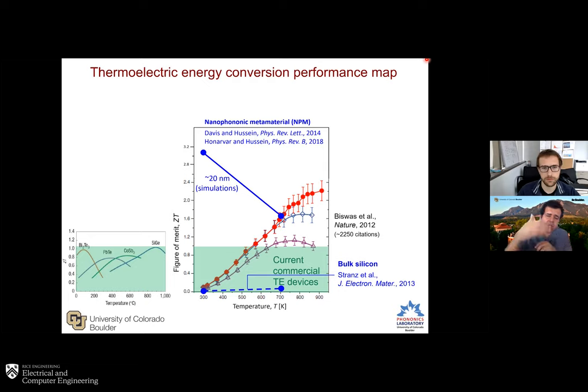So this is, of course, based on simulations. It's not experimentally validated yet. And it's based on nanostructures that are quite small, on the order of 20 nanometers. So for practical purposes, of course, we need them to be larger, but at least it shows the potential. These are a couple of references where we demonstrate how we can project such a significant increase